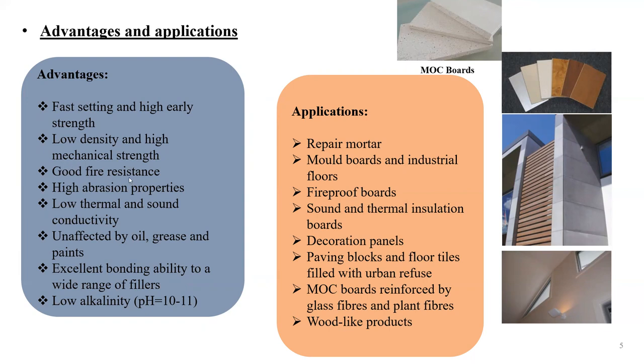Another inherent property is good fire resistance. So inherently, it is a very good fire resistant material. And also, it has high abrasion resistance and low thermal and sound conductivity. So this is good for thermal and soundproof boards, for decoration boards. And also, it is unaffected by oil, grease, and paint. Excellent bonding ability to a wide range of fillers, also including waste, and also low alkalinity.